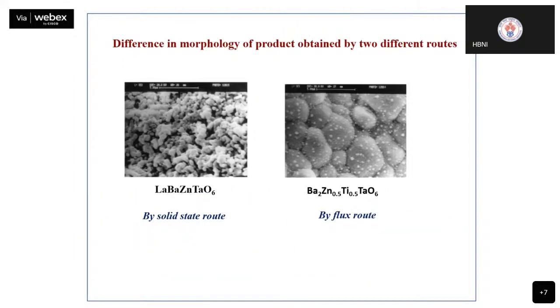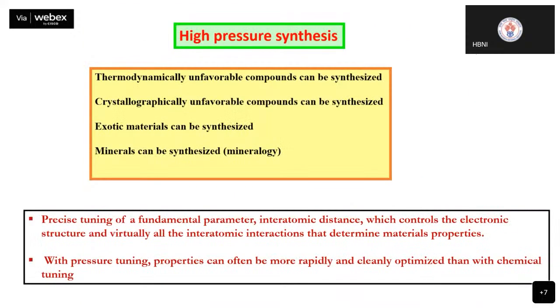Okay. Again, showing how it affects the morphology. This particular product is made by solid state route. And density, as you can see, is not very high. You have a lot of pores, the black things that you can see. This is obtained by flux route. The particle size is not homogeneous, but the product is dense and the morphology is much better defined.